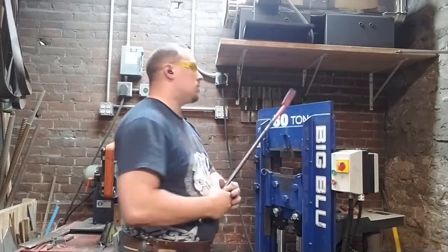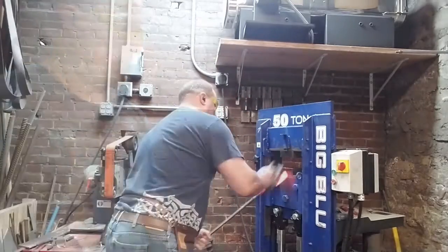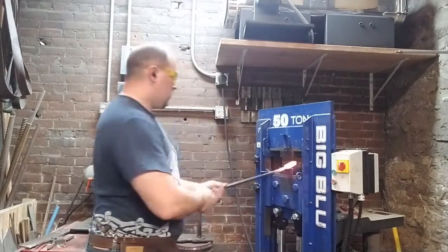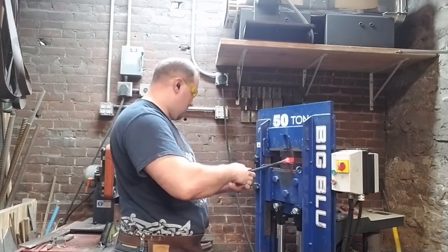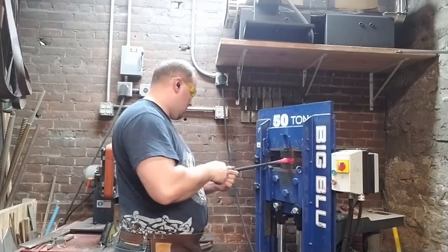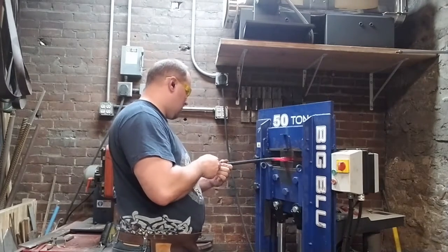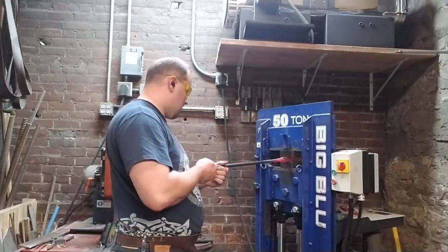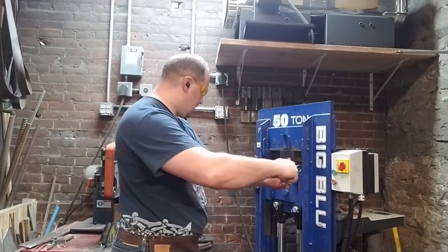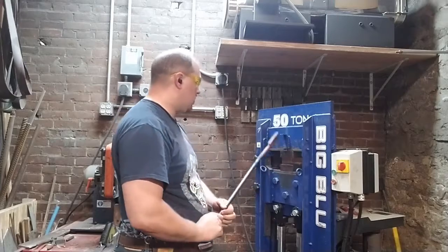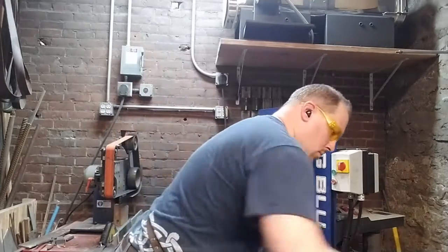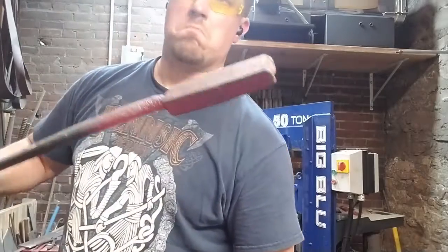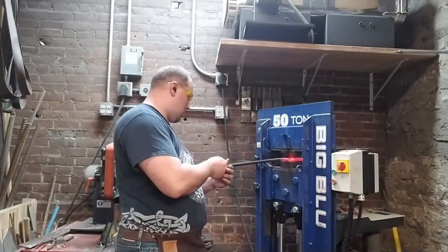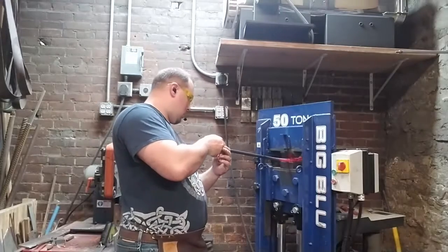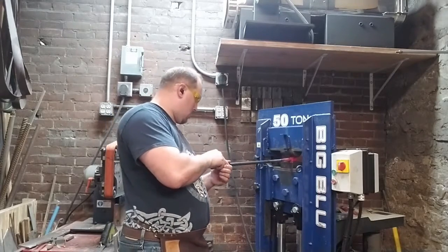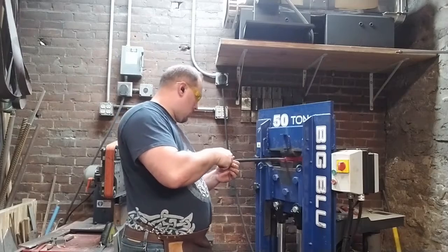As you saw, I went ahead and I set the welds with a couple of heats on the anvil, and then I'm moving over to the forge. And those welds set very nicely. We've got a very contiguous material. And from here on, we're going to be forging in both directions, in the plane of the weld and perpendicular to the plane of the weld. And that means those seams are very likely to want to open up. So we're going to have to be careful with that. We're going to have to work hot. We're going to have to work carefully. We're probably going to have to reflux a number of times.